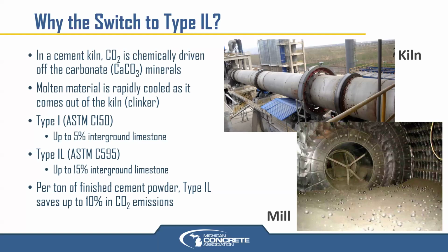ASTM C 150 has been around for 100 years or so. Blended cements fall under ASTM C 595, and one of those types is Type 1L. The 1 being that it's very similar to the old Type 1 of ASTM C 150, but the L meaning that it has higher amounts of limestone. And in that case, that specification allows up to 15% ground limestone introduced to the mill, obviously with the clinker and whatever other ingredients the cement manufacturer puts in to help control their product. So that's the main difference.